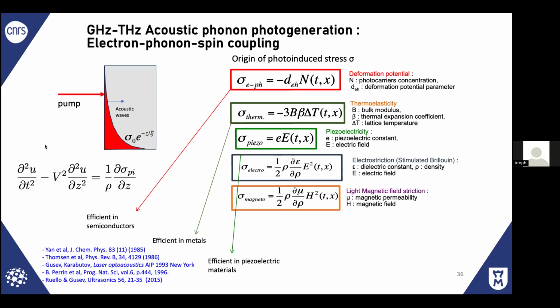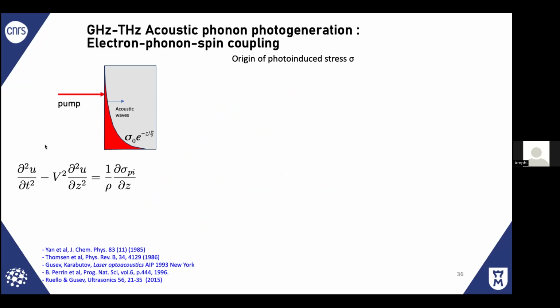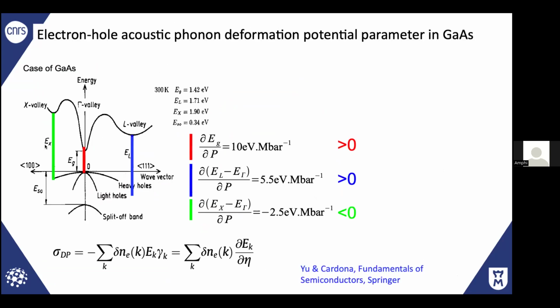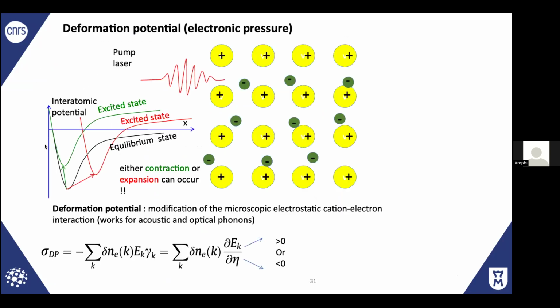Generation, if you excite in the bound state, because of the terms that you described, what remains? Is your question referring to deformation potential? Yes. That is a very simplified sketch. Of course, the deformation potential is written for, let's say, acoustic phonon, but you can have also the same situation for optical phonon. Sometimes when you shine light, you induce very different interband transitions, so you can populate different valleys. Sometimes what you observe is just the consequence of the contribution of different deformation potentials, not only one, because the electronic Grüneisen parameter depends on the k vector where you put the electron.